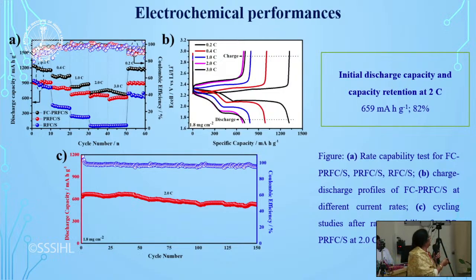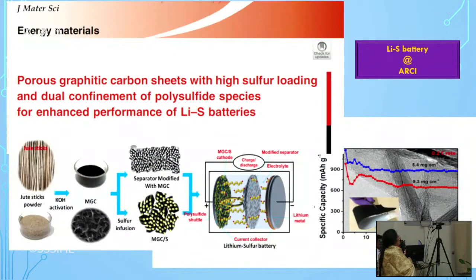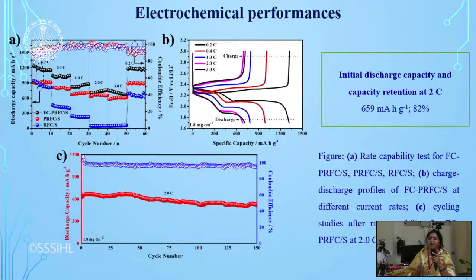So you can see over here at 2C, I don't know if you know 2C, 1C and all. So it is how quickly you charge it. So 0.1C, 0.2C, we calculate in those terms. So how quickly you charge it, how slowly you charge it. So at 2C rate, you can see that it is quite stable. Then we have increased even the mass loading. We have taken to 4 milligrams per centimeter square, and even with high mass loading, it has shown very good performance. Now, we patented it, we published, and now we are in the process of upscaling, and the industry is waiting for us to show even at 1 kilogram quantity.